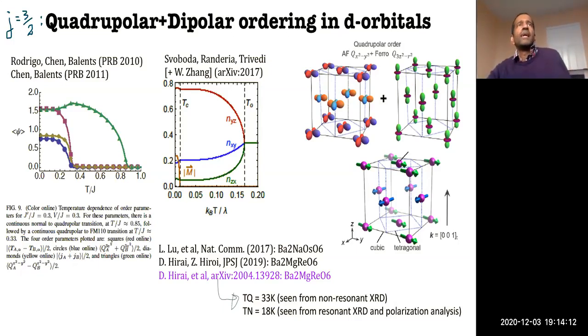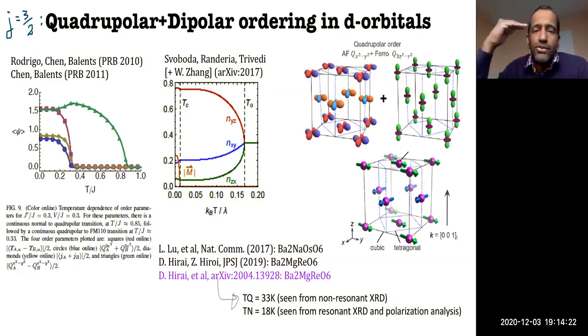In terms of the excitation spectrum, it turns out there are somewhat subtle signatures in the low energy phonon modes, but it's not like there is a clear soft phonon that you see. You would think that this should be like a cubic to tetragonal transition, for instance, right? But the signatures are quite weak and subtle in the low energy phonon modes that we've been looking at together with Bruce Gaulin.